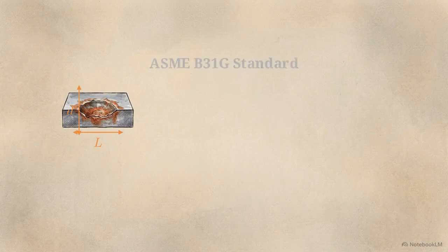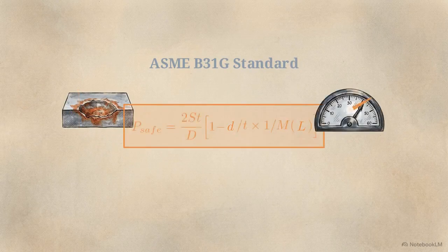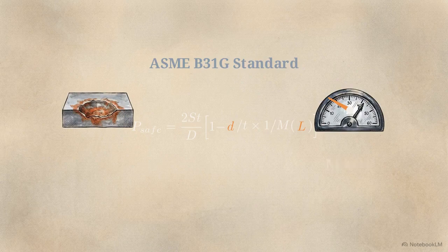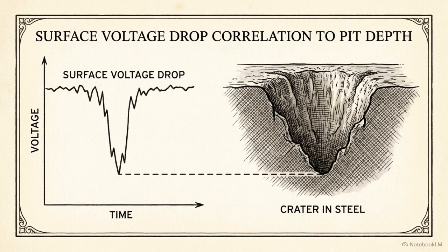They then apply the B31G engineering formula, converting the pit depth and length into the pipe's remaining maximum allowable operating pressure. Direct examination closes the loop. It validates the inferential electrical data, proving that measured surface voltage drops directly correlate to a loss in mechanical strength.